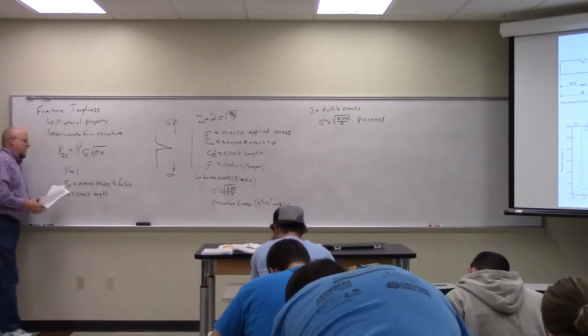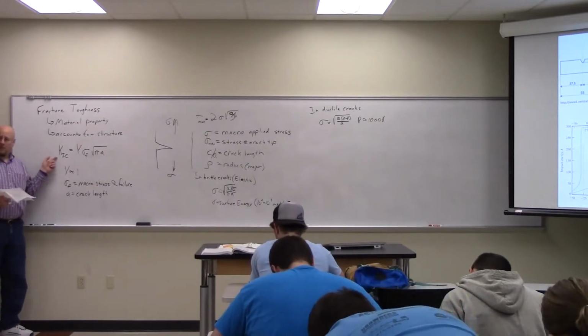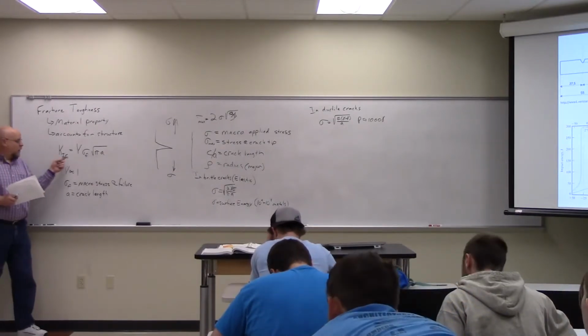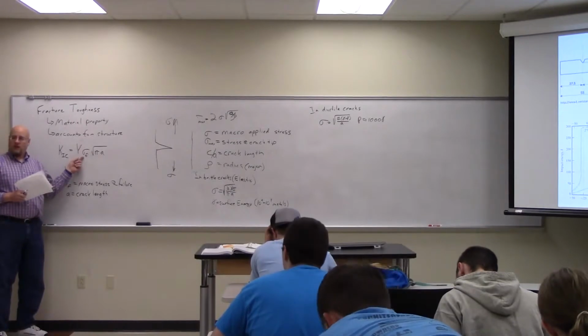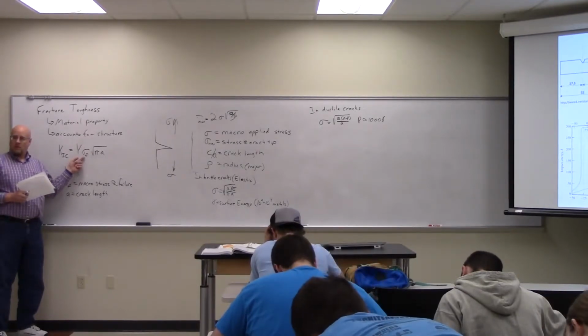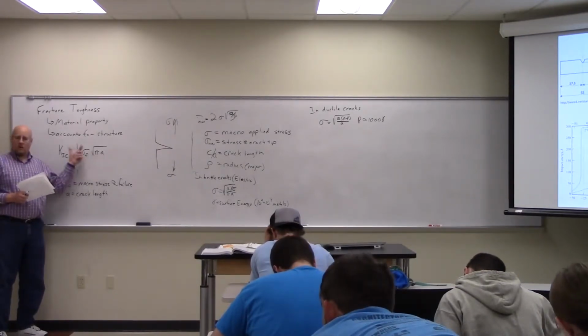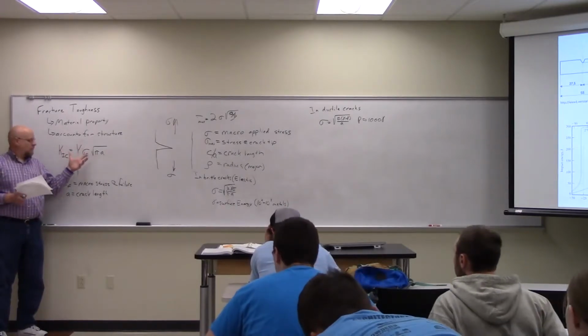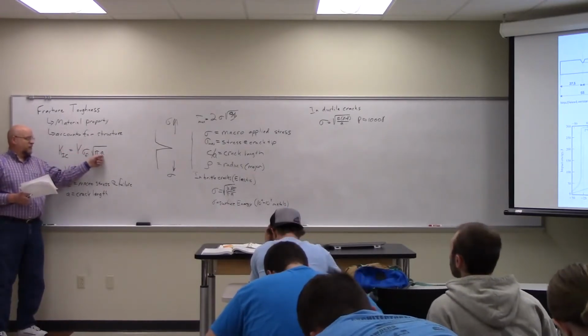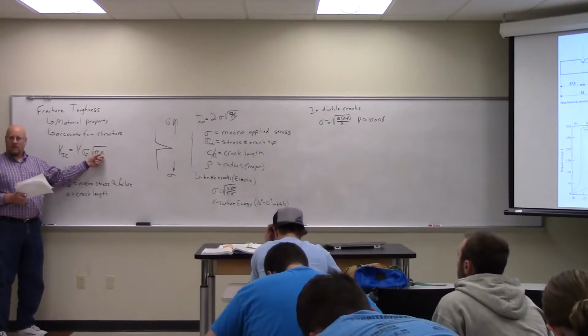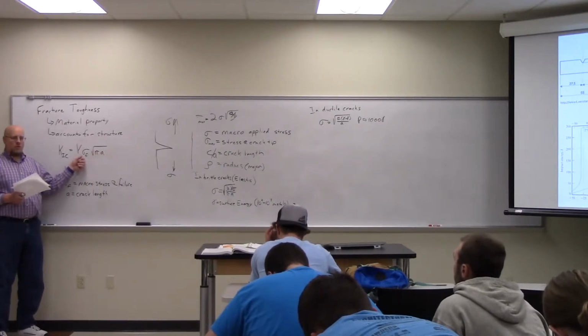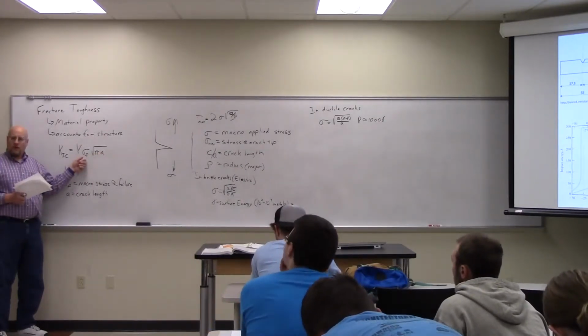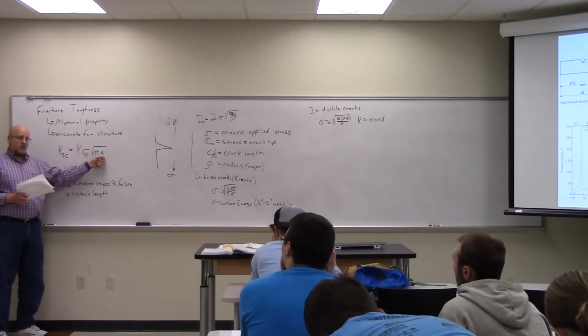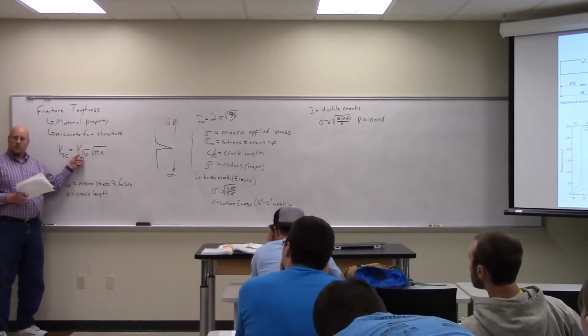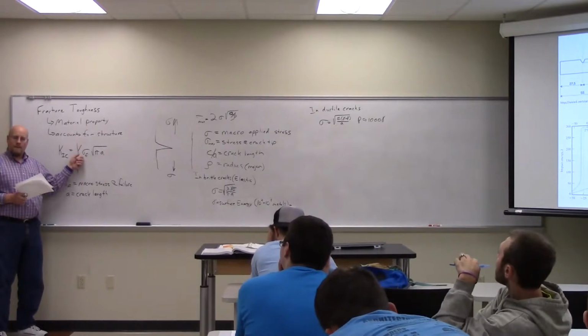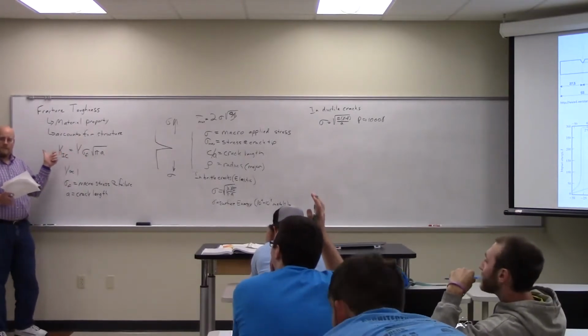So what does that mean? That is a fixed parameter for a material. So as I increase the applied stress, I have to decrease the a in order to maintain the system. So if I have small cracks in the surface, it'll tolerate a larger stress before it fails. If I have large cracks, it will only tolerate small stress before it fails. Does that make sense? Okay, yes.